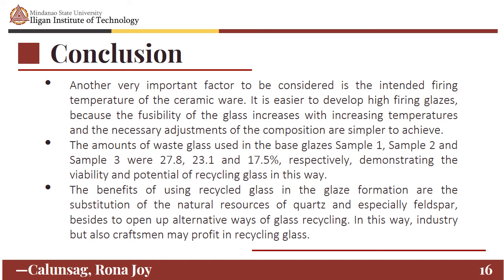The amounts of waste glass used in the base glazes sample 1, sample 2, and sample 3 were 27.8, 23.1, and 17.5%, respectively, demonstrating the viability and potential of recycling glass in this way. The benefits of using recycled glass in the glaze formulation are the substitution of the natural resources of quartz and especially feldspar, besides opening up alternative ways of glass recycling. In this way, industry but also craftsmen may profit from recycling glass.